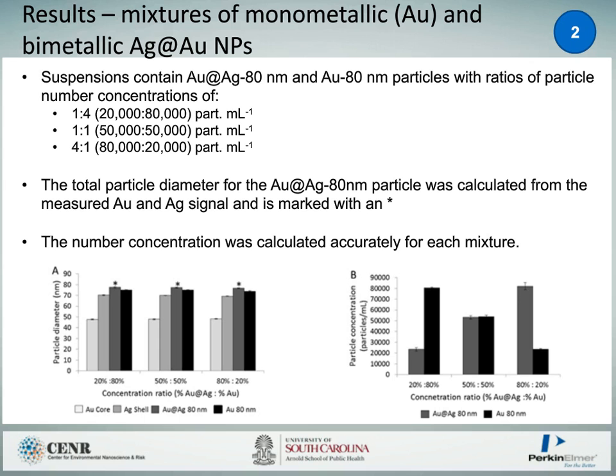Here we're looking at suspensions of gold core silver shell nanoparticles, total of 80 nanometers. But here we're looking at a core of 50 nanometers and a shell of 15 nanometers, and an 80 nanometer gold particle. We put 3 different ratios into the FFF and collected the fraction. So we have a 1:4, a 1:1, and a 4:1.